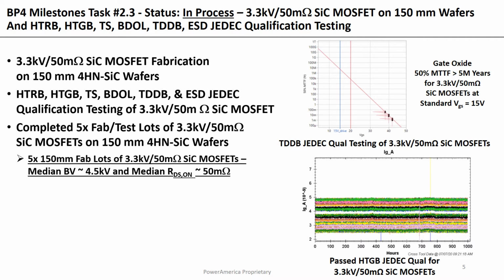Thus far on the BP4 project, we have completed 5 fabrication lots, including testing of 3.3 kV 50 milliohm silicon carbide MOSFETs on 150 millimeter wafers. The median breakdown voltage is 4.5 kilovolts, and the median RDS(on) is 50 milliohms.